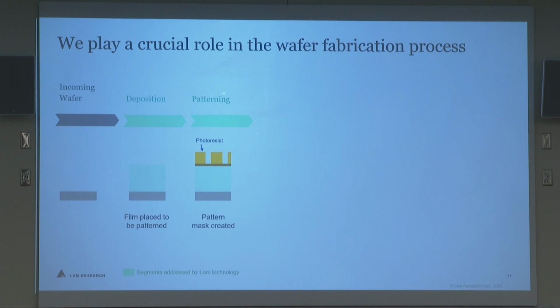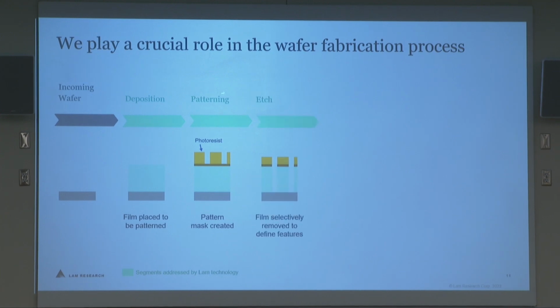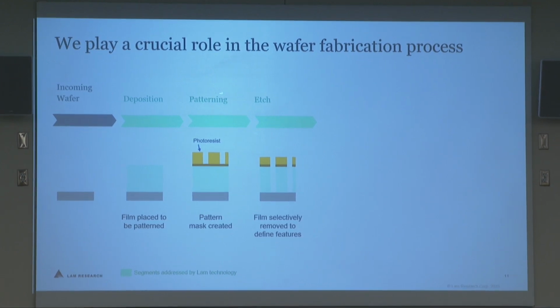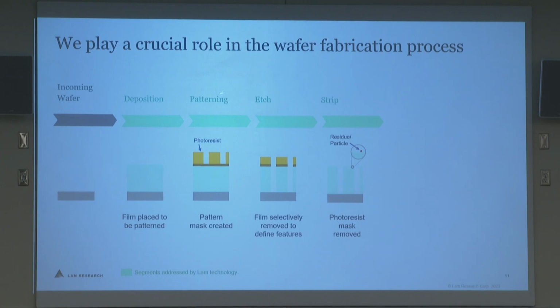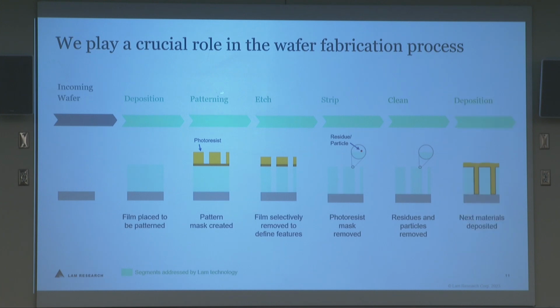You expose a photoresist. It can be positive or negative, so you can either remove the part that gets exposed, or the opposite, you remove the part that doesn't get exposed. And now you've got a mask, essentially. And then you etch where that material's been exposed to remove it. So now you have a 3-dimensional structure. You strip to remove that photoresist and any extra masking layers you might have used. And then you have to clean it to remove the residue from all of those processes. So all of those, the deposition, the resist used in the patterning, etch, strip, and clean are all products that Lam designs and sells to our customers in the fab. And then you repeat that. So that gets repeated to make up the 700 steps. The next layer comes down and you go with your next level of materials.